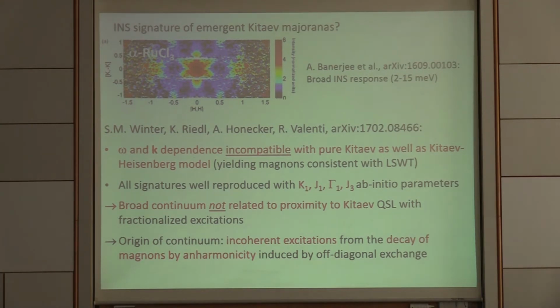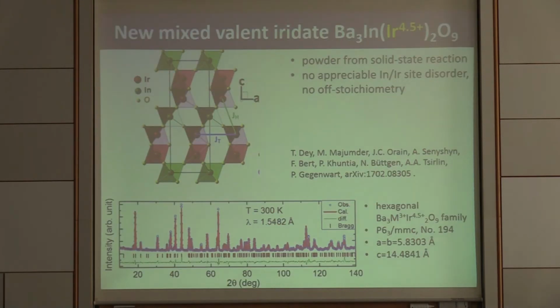And that tells us that in general we should be careful when considering spin-orbit coupled moments with highly anisotropic exchange, namely that if we experimentally observe a very broad excitation spectrum, it may also result just from the anharmonic decay of the magnons. So now I'd like to introduce two new materials.